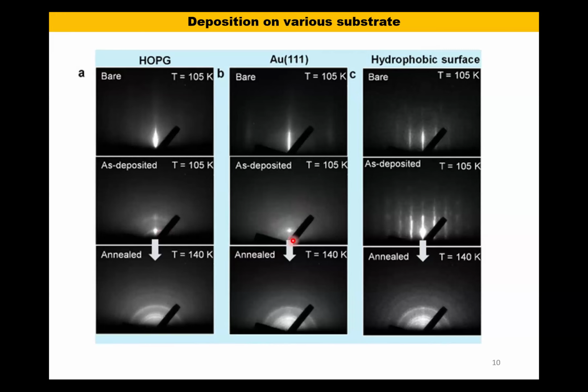So in these two cases, the surface is dominated by water. Here the surface is dominated by both THF and water. But in this case, the surface is dominated by purely THF. So this is the diffraction you are seeing, for pure THF crystalline solid. When we thermally anneal, this THF will obviously dissolve at a higher temperature, so the surface will be different and you will get a uniform surface at higher temperature.